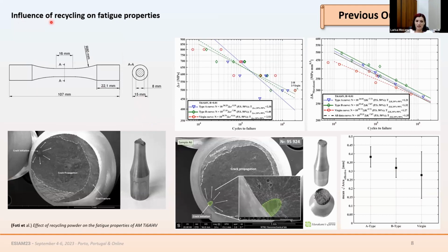We also investigated the influence of recycling on the fatigue properties. We performed fatigue tests on the three sets of components, and here too we saw no particular relevance of the recycling processes. In this first graph, the nominal stress range versus the number of cycles, we saw no particular difference between the three types of components. The only difference we saw is that the data scatter is quite high, and this is probably due to the high amount of defects inside the components.